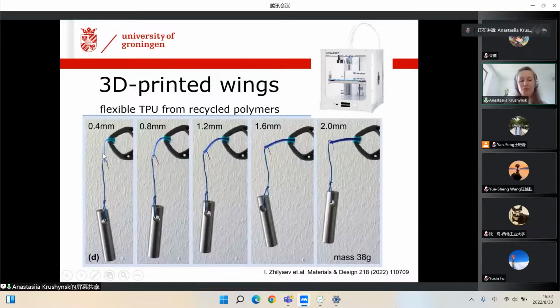So then we have 2 printed layers. You see that the material is very flexible, and at the same time, it exhibits fully reversible deformations. So when we remove the mass, it returns to its initial position and shape. But if the number of printed layers increases gradually, you see that the material behaves more and more rigidly. So this allows us to make a wing model made from one material, so this TPU or recycled polymer, but at the same time control the rigidity and flexibility of the material by changing the number of printed layers.